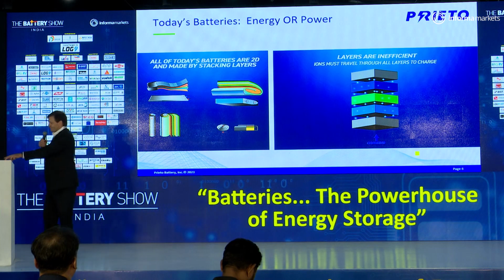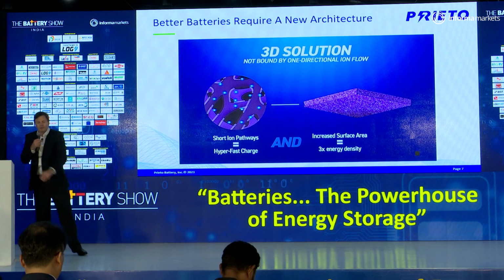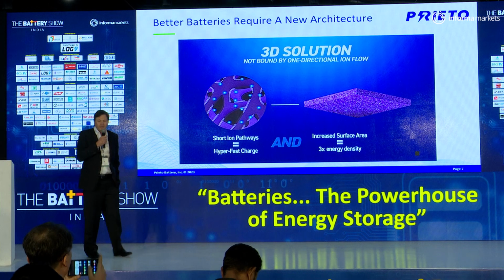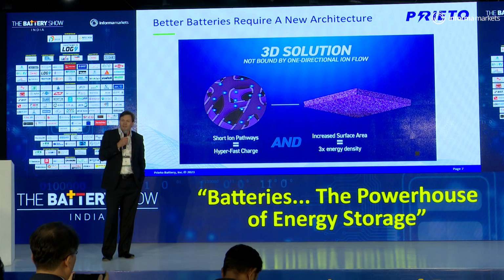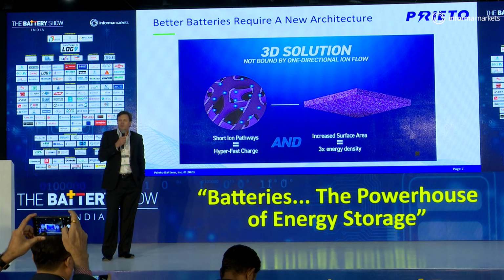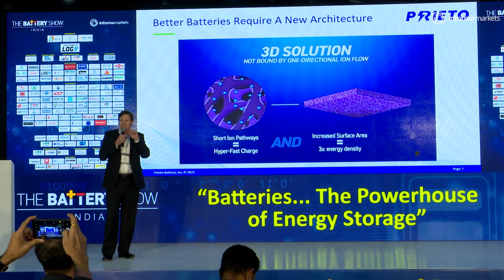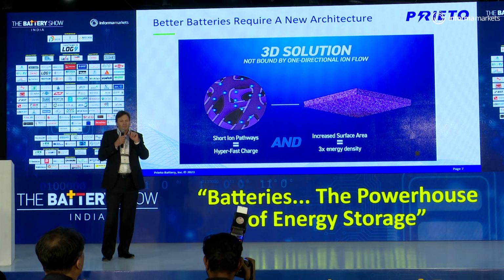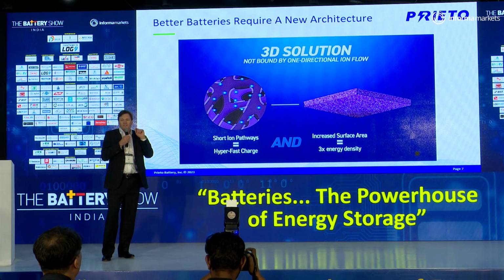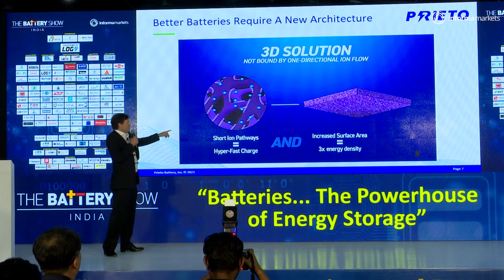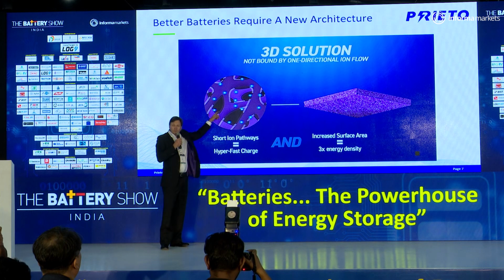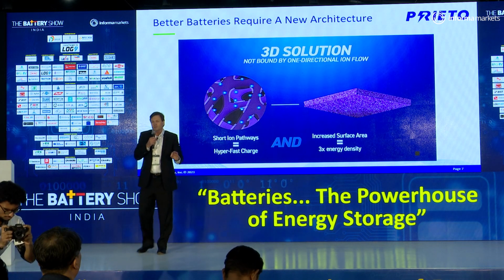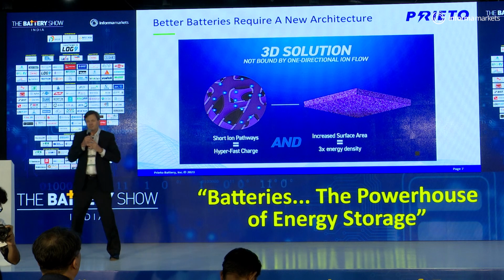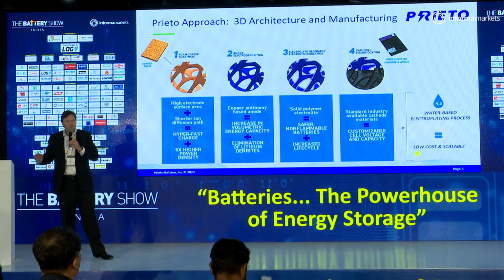And how do we do that? We've created this 3D battery. We start with a highly porous structure that has a high surface area. Then we coat the individual strands of that porous substrate with a very, very thin layer of anode, a very thin separator, and a very thin cathode. So you have a very short pathway for the lithium ion to go back and forth, so it's a super fast charge. Yet you have a lot of surface area within that structure.